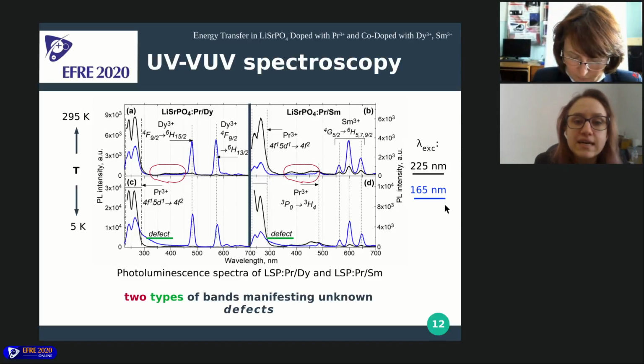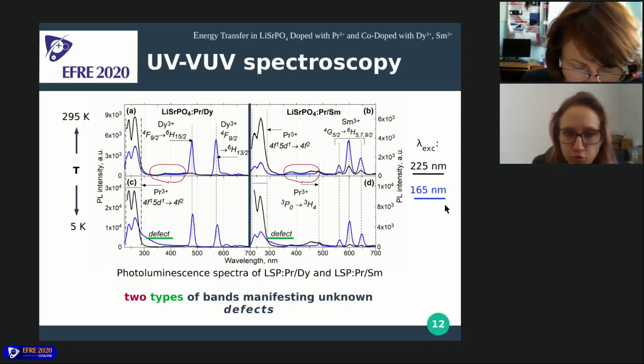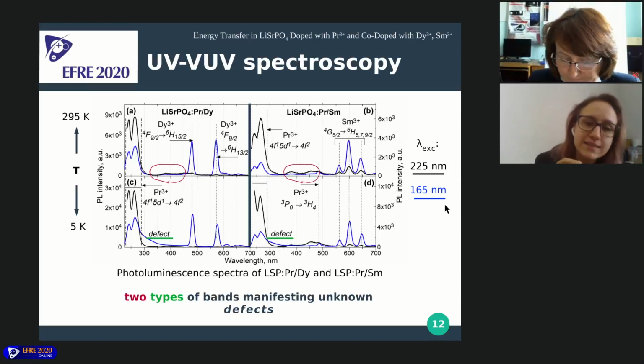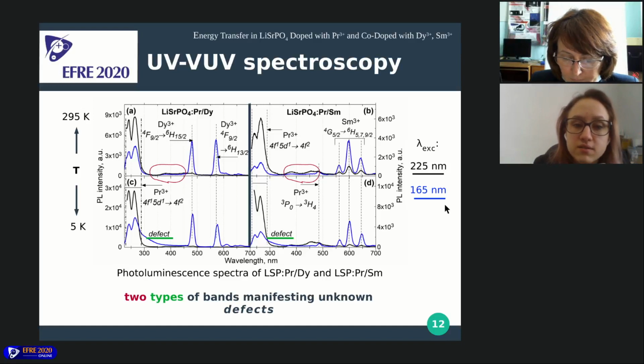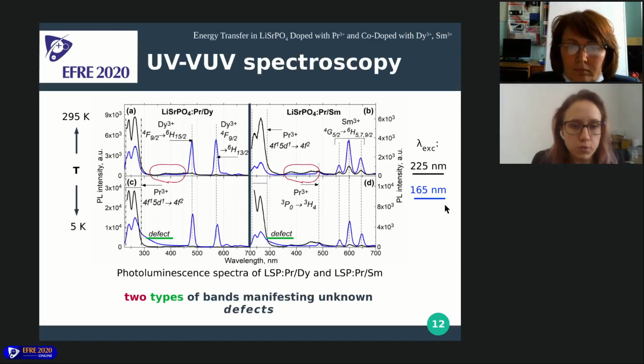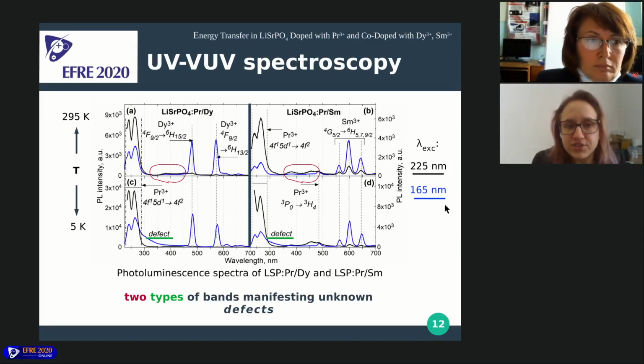But under direct excitation of praseodymium-3+ straight into its 4f5d band, which is 225 nanometers, we don't see these emission lines of dysprosium, nor samarium. But in the case of samarium, we can actually see some weak emission in the red region, which is peculiar because it probably indicates some energy transfer processes from praseodymium to samarium. And it is also very important to point out that we can observe some unknown additional emission, which cannot be assigned to the emission of these activators itself.